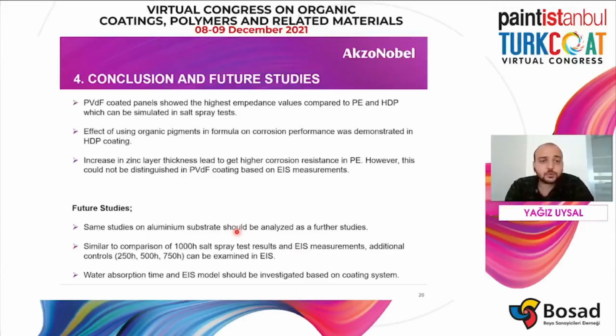I can conclude my presentation as follows. The PVDF coated panels show the highest impedance value compared to polyester and HDP ones, which we can simulate in the salt spray test. The effect of using organic pigments in the formula on corrosion performance was demonstrated in HDP polyester coating. An increase in the zinc layer thickness led to higher corrosion resistance in polyester. However, we couldn't distinguish it in PVDF coating based on the electrochemical impedance spectroscopy measurements, while there are small differences in the accelerated salt spray test.